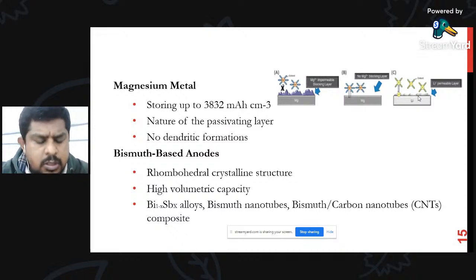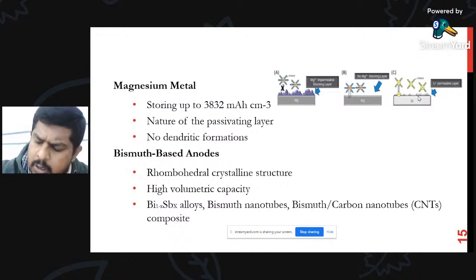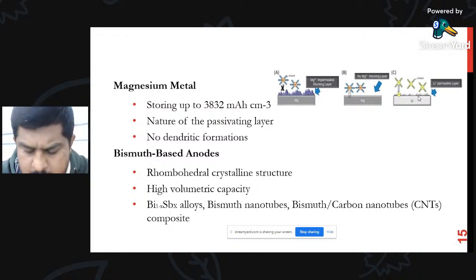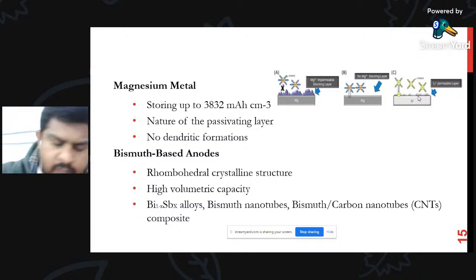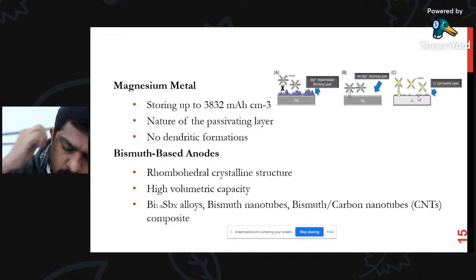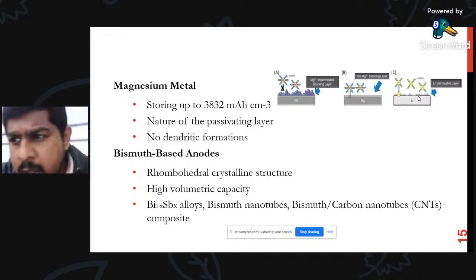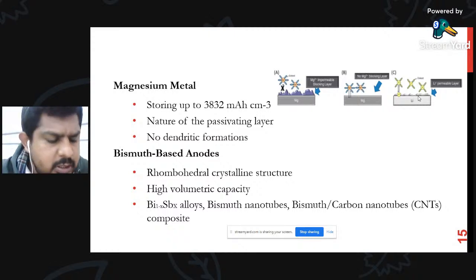After a period of something like 100 cycles or 200 cycles, the capacity is getting faded. There is a researcher who did research work on bismuth anode. If it is pure bismuth, the energy density is something like 257. After 100 cycles, it is reduced to 220. So the specific density values also decrease here.